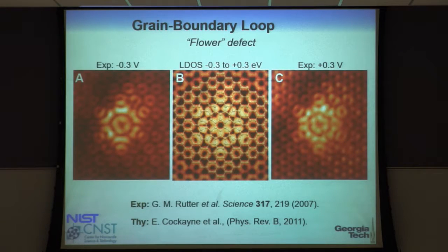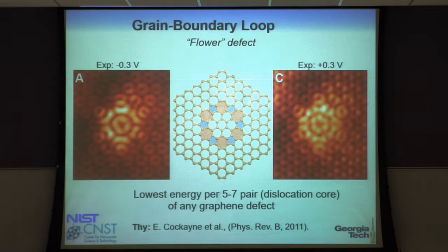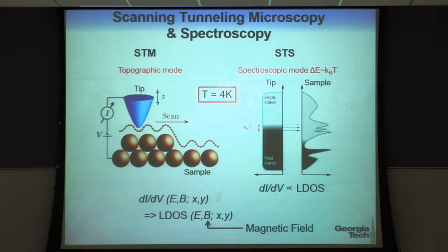And this is a density functional calculation done by Eric Cockayne at NIST. And what he found was that this flower defect is in fact perfect graphene, but in the middle you take these 7 hexagons and you rotate them by 30 degrees and then connect them back up. And when you connect them back up, you get 7-fold, 5-fold, 7-fold, 5-fold pairs, which can be viewed as each one the core of a dislocation. And so this grain boundary turns out to be incredibly low energy to form and just really interesting. More will happen, I'm sure of it.